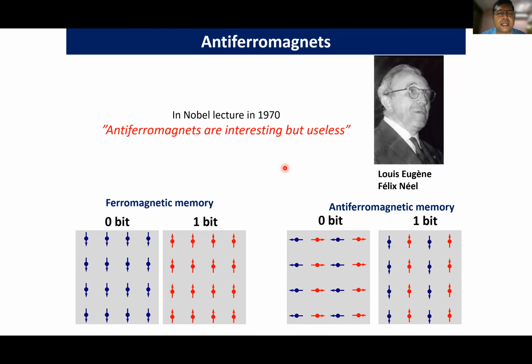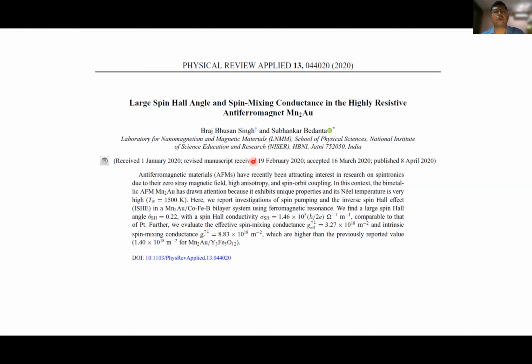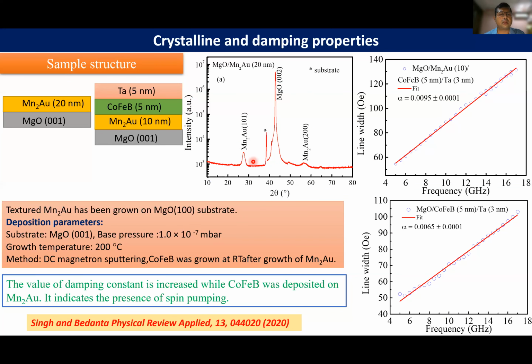Manganese gold is a candidate, of course, because it has a very high Néel temperature, like 1500 Kelvin, and people have shown that it exhibits very nice properties with respect to terahertz spectroscopy, terahertz dynamics, and so on. Let me quickly go to our work, where we prepared these manganese gold thin films adjacent to cobalt iron boron thin films, a low damping material. We could stabilize the stoichiometry of the manganese gold very nicely on an MgO substrate, and performed FMR and the inverse spin Hall effect.